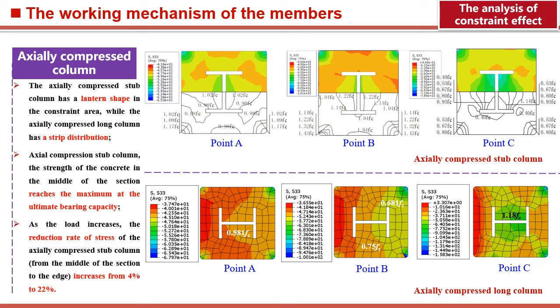materials. These figures describe the stress contours of stub and long columns under axial compression. After the steel yields, the profile itself has a very significant restraint effect on the concrete. At the same time, this interaction acts as a support to the inner CFRP, so it can give full play to its compression performance. After reaching the peak load, the stress gradient gradually accelerates from the center of the interface to the edge, indicating that the restraint effect is gradually reduced.